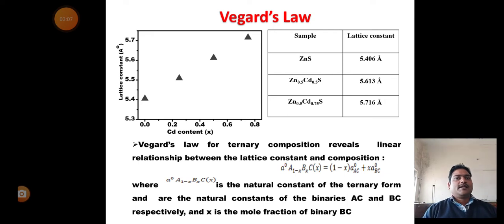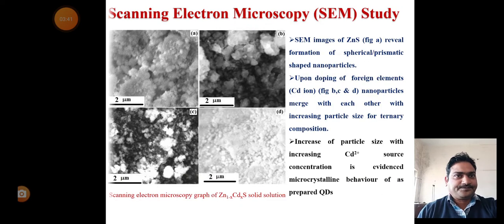Vegard's law shows a linear relationship between lattice constant and cadmium content: as the cadmium concentration increases in zinc sulfide, the lattice constant increases linearly. This shows the alloying effect of the zinc cadmium sulfide samples, and this result indicates that zinc cadmium sulfide is not a mixture of zinc sulfide and cadmium sulfide, but it is a zinc cadmium sulfide solid solution.